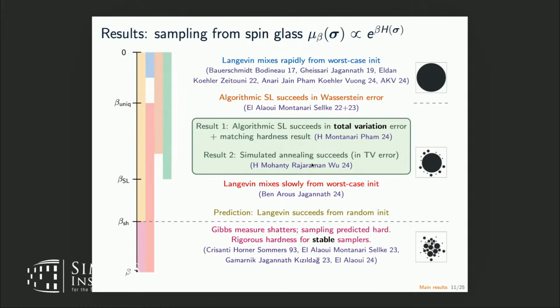And our second result is that in the same range of temperatures, simulated annealing will also succeed. We expect that simulated annealing will work all the way up to shattering, and the fact that the result stops here is an artifact of the proof.